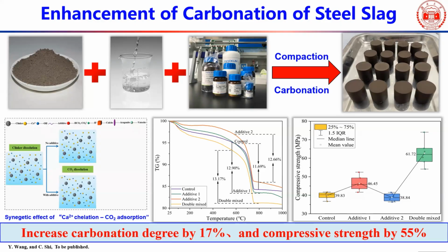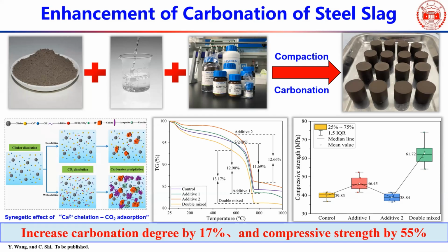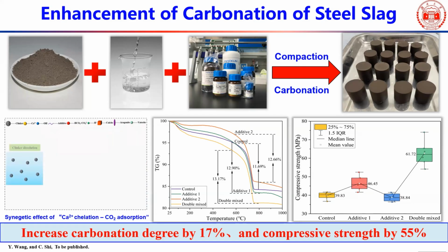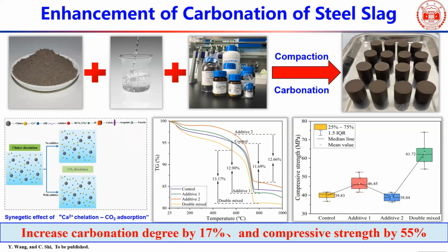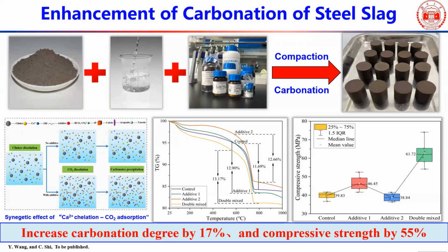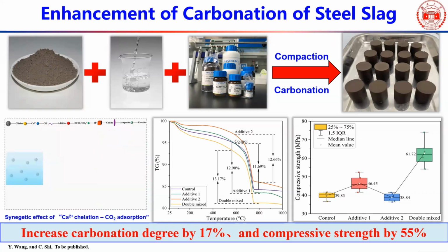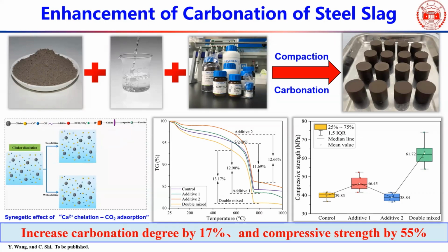You can see here we use some chelate and also some carbonation enhancement additive. Typically we can get only about 40 megapascal, but here we got 60 to 70 megapascal strength. With such a high strength, I think we can have much broader applications for this technology.